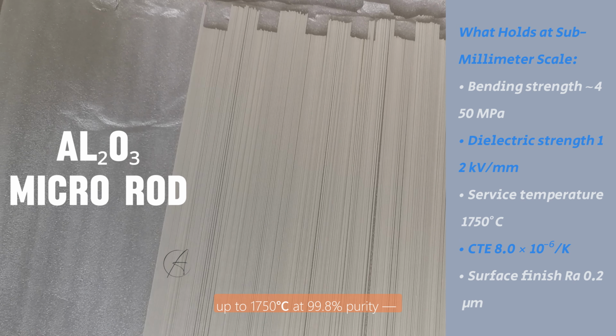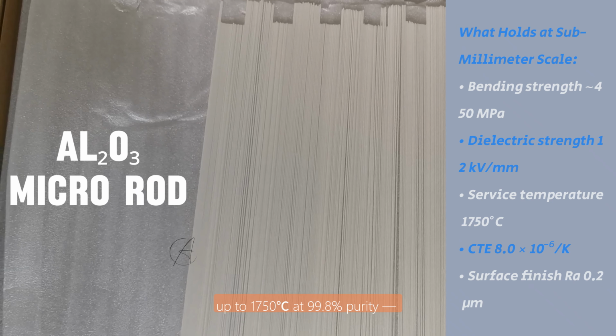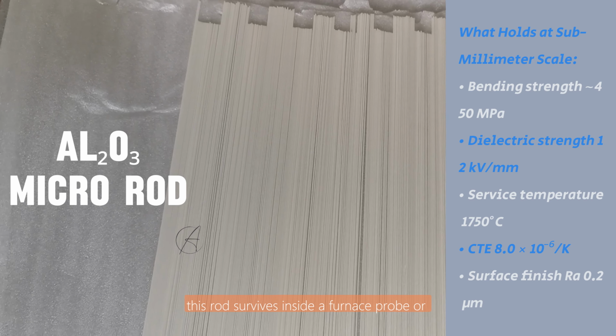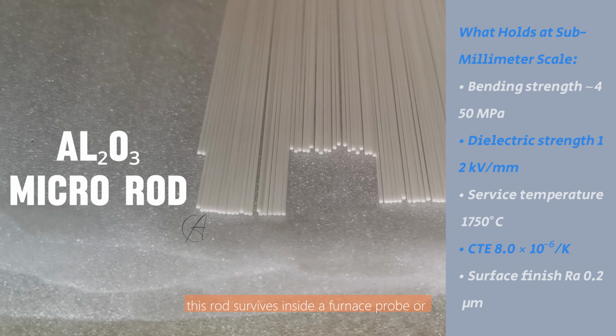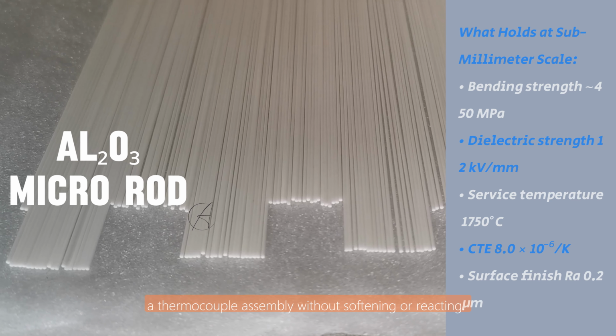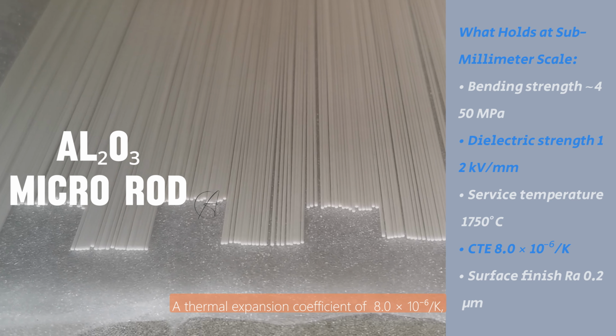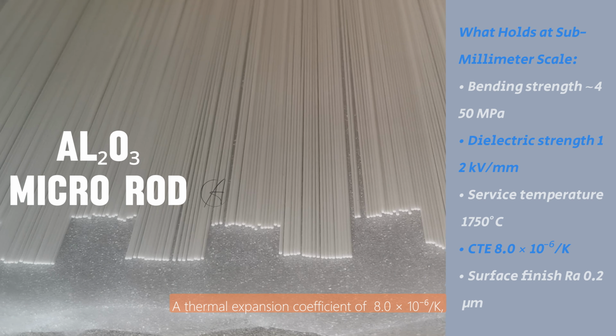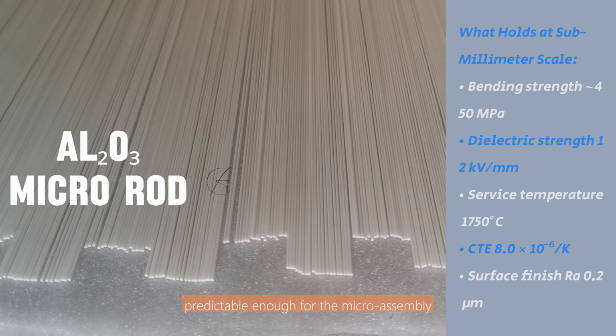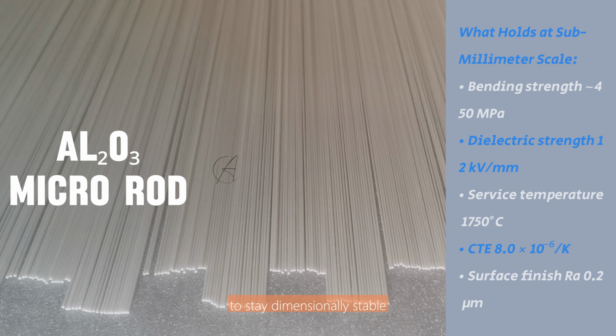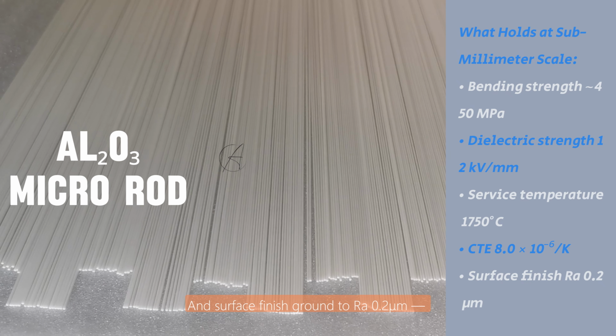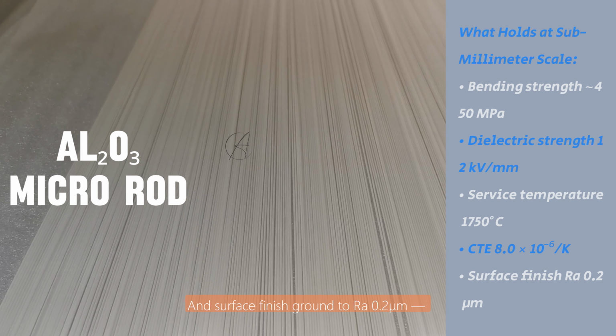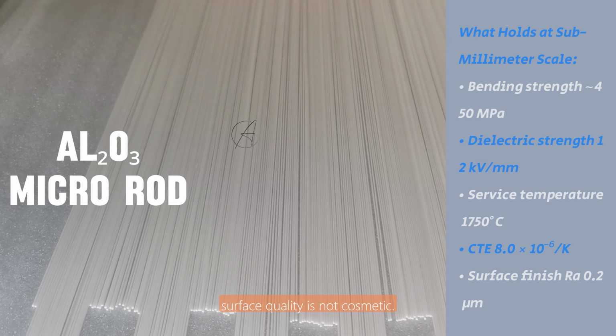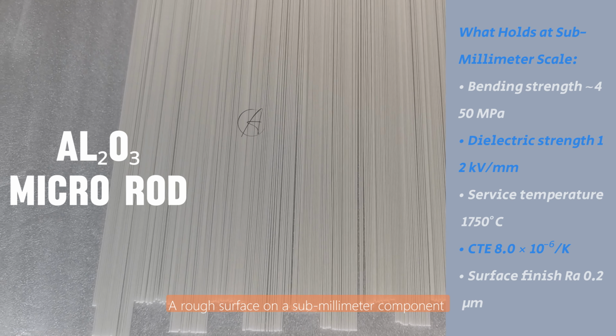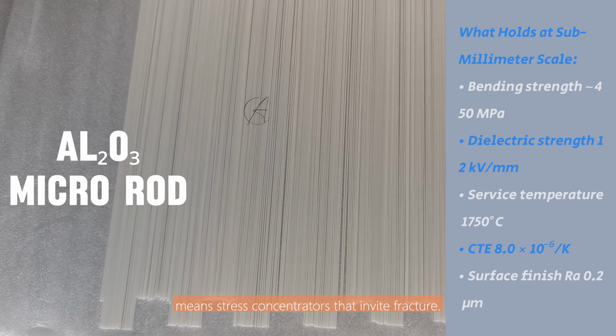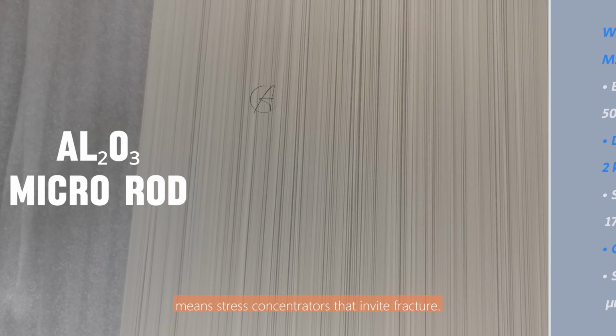Continuous service temperature up to 1750 degrees Celsius at 99.8% purity. This rod survives inside a furnace probe or a thermocouple assembly without softening or reacting. A thermal expansion coefficient of 8 times 10 to the -6 per Kelvin, predictable enough for the microassembly to stay dimensionally stable through thermal cycling. And surface finish ground to Ra 0.2 micrometers. On a rod this small, surface quality is not cosmetic. A rough surface on a sub-millimeter component means stress concentrators that invite fracture.